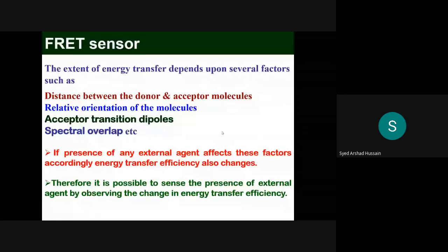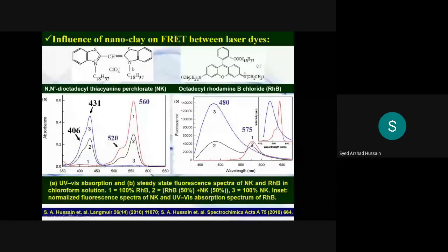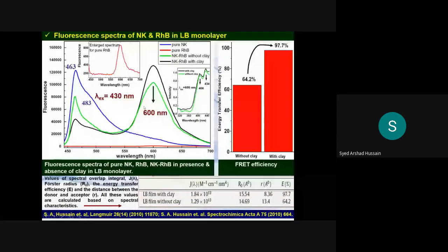So it's very advantageous. So in one example, we studied energy transfer between a thiocyanin derivative and a rhodamine derivative. And we observed that in normal solution, no energy transfer occurred. But when the material was transferred into films, LB films, energy transfer occurred, 64%. That is, the donor absorbs energy from the source by direct excitation and transfers a part of this to the acceptor. We calculated the efficiency in the absence of clay, it was 64.2%, but in the presence of clay we found that efficiency increases to 97.7%.